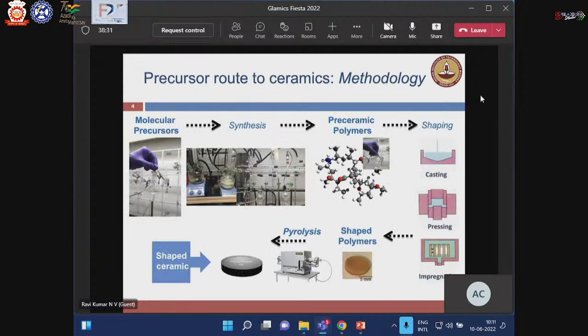Just to give you an idea, for the young researchers who may not know how ceramics are produced through precursor route, we start with molecular precursors. So we start with individual monomers. So it's completely wet chemistry. We convert monomers to polymers, and these preceramic polymers are then shaped into various shapes depending on what we are interested in. These preceramic polymers, which are organic polymers, are then subsequently pyrolyzed at high temperatures, where they are converted to inorganic amorphous ceramics. Of course, further heat treatment leads to stable crystalline phases.